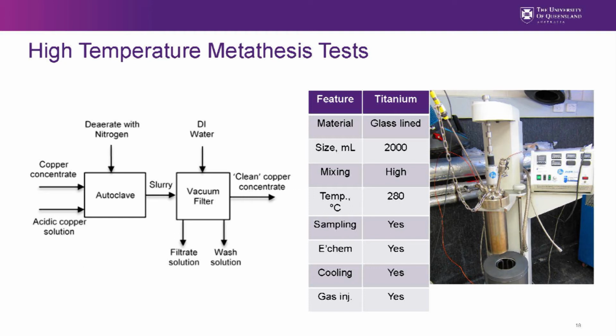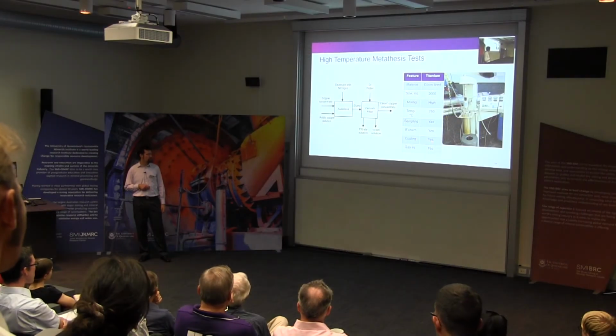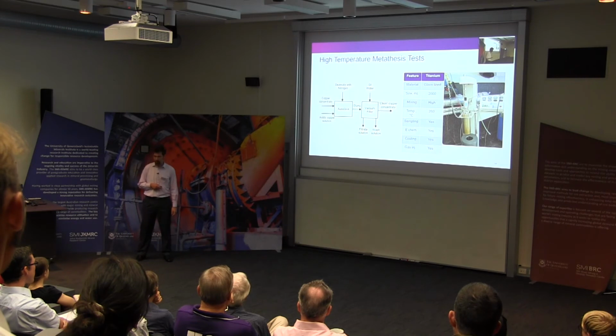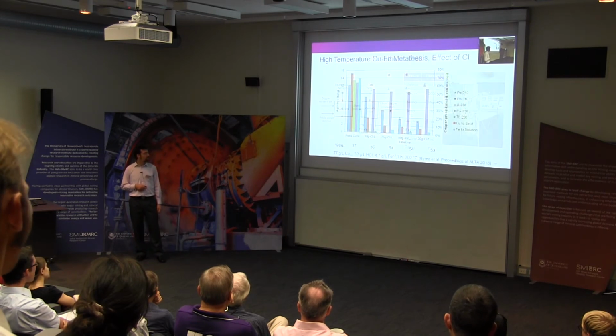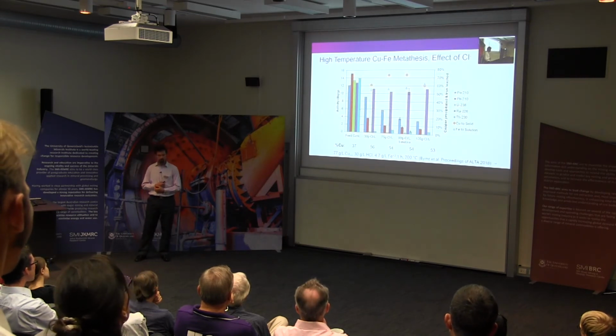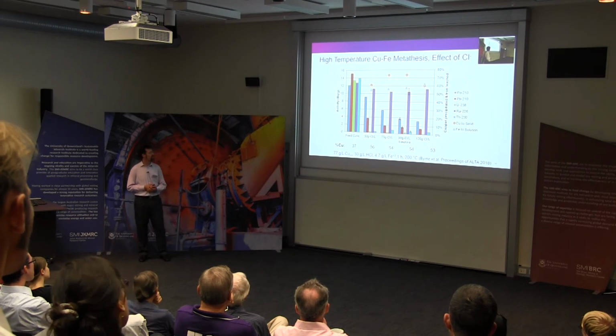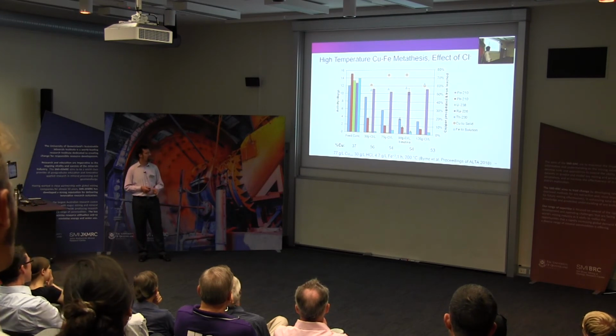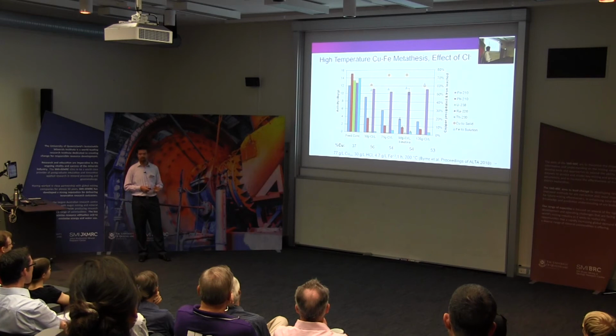So this is a silver-silver chloride reference electrode, which can be inserted into the slurry during the reaction, so we can monitor the Eh, essentially. The autoclave has internal cooling, and we could potentially inject gases if needed. So this is the result from that type of experiment. This slide's a little bit busy, so I'll take a second to just go through it.